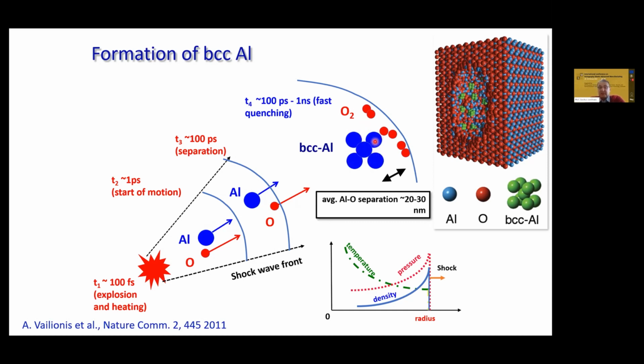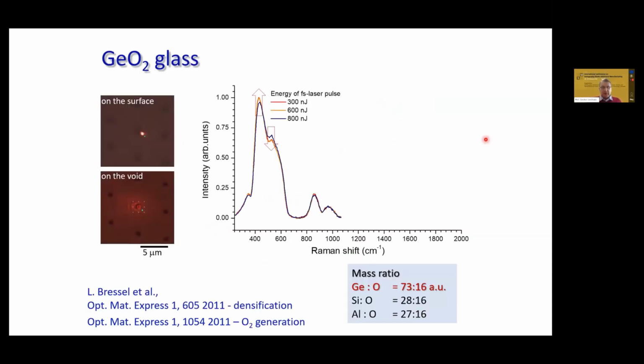Nanocrystallites are around 20 nanometers in size. Some oxygen should be present nearby. It can form new phases in sapphire, but that was not seen in this experiment. But I will show in the next slide where we detect oxygen inside the volumes which we modify. So we took glass, which has a larger ratio between masses of elements.